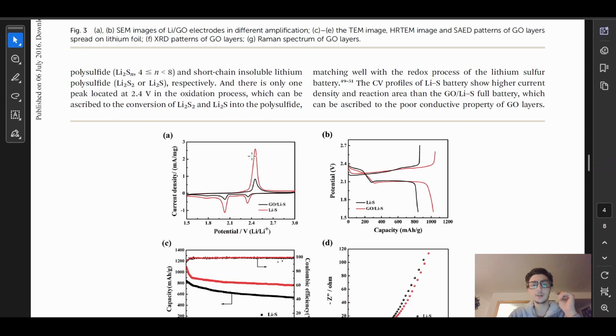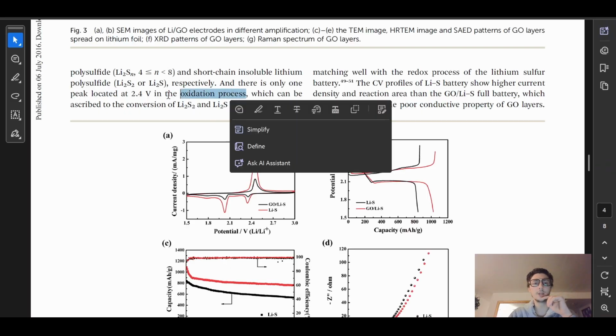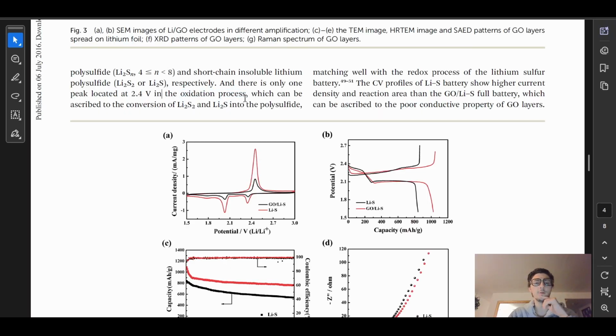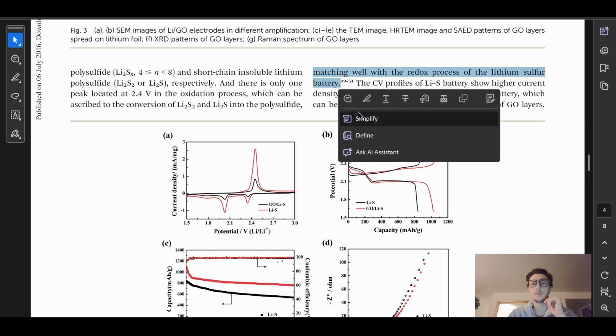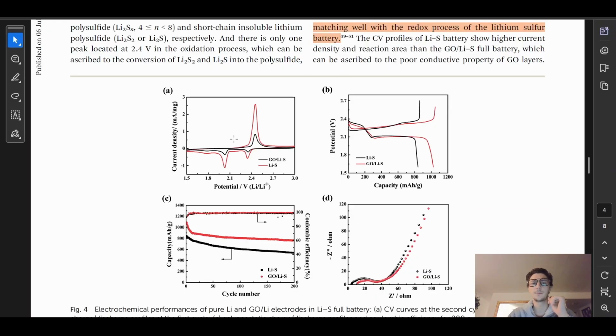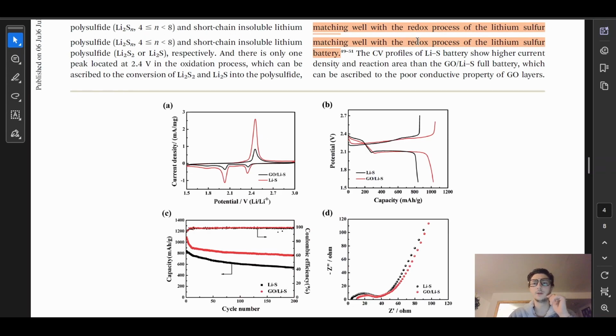Both have reduction peaks, and they both have one oxidation peak at the 2.4 volt, which can be ascribed to the conversion of Li2S2 and Li2S into the polysulfide, matching well with the redox process of lithium sulfur battery. Okay, matching well with the lithium sulfur battery. I'm just going to highlight that because that's interesting. And they're talking about this graph here, the CV curve.